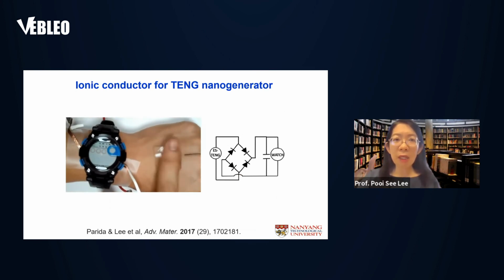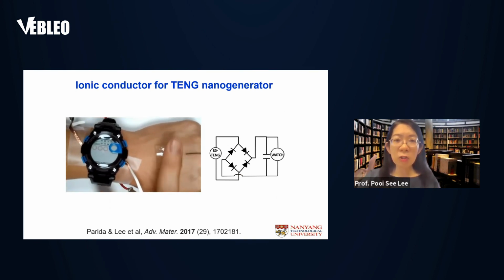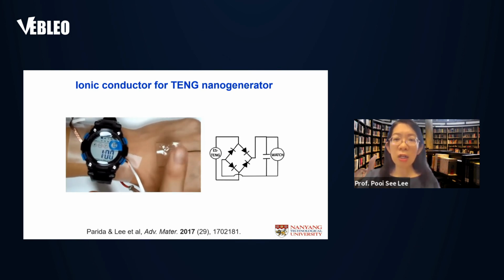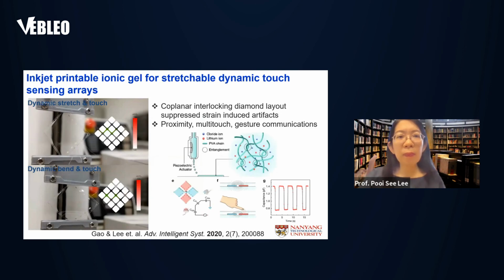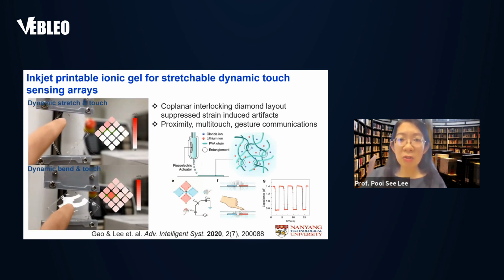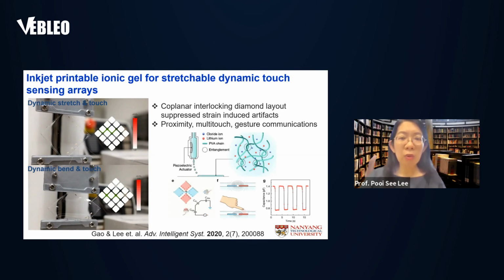So by simple tapping, for example, without any energy source, it can power up the digital watch as indicated in this demonstrator. And not only that, we also work on printing the ionic gel to create a transparent array of touch sensors that can operate during a dynamic bending and stretching condition without affecting the touch sensing signal. And this is due to the innovative coplanar interlocking diamond layout, which suppresses the strain-induced artifact when it augments the sensing performance.